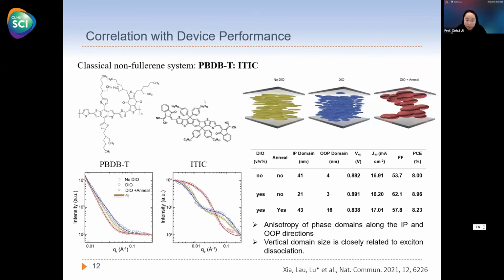So by this, for the first time, we can extract the out-of-plane nanophase separation information of the sample. So we use this to study the classical PBDB-T:ITIC system. We find that inside this organic active layer, the domains are not isotropic. In the vertical direction, the phase separation domain size is shorter than in the in-plane direction. So this will become the bottleneck for the exciton dissociation. So we can understand the device behavior in a new window, basically, to understand it in the vertical direction because it's shorter.